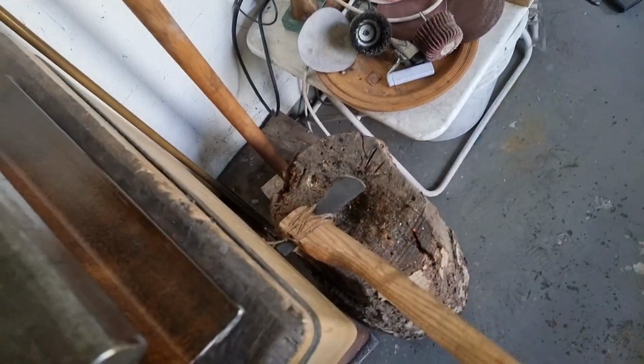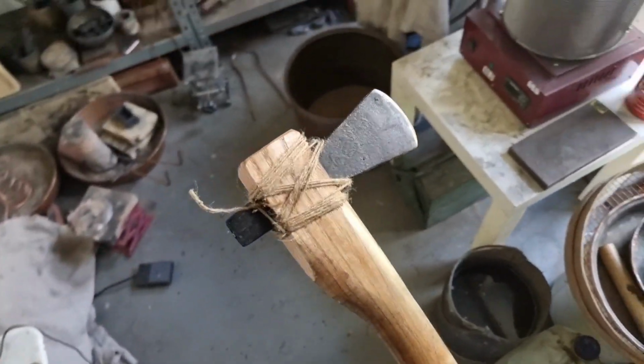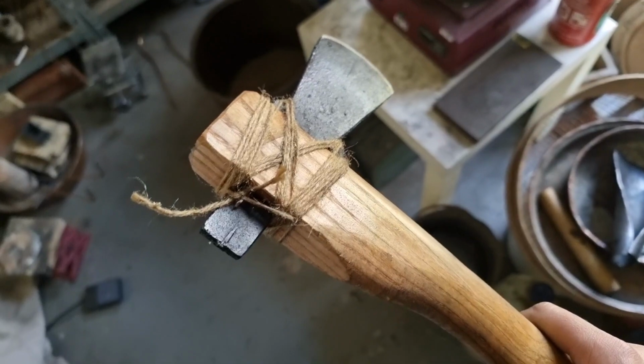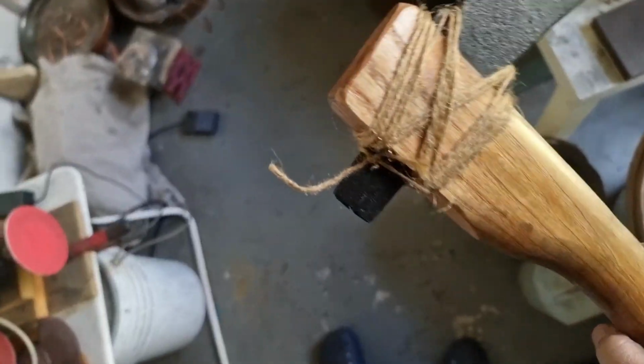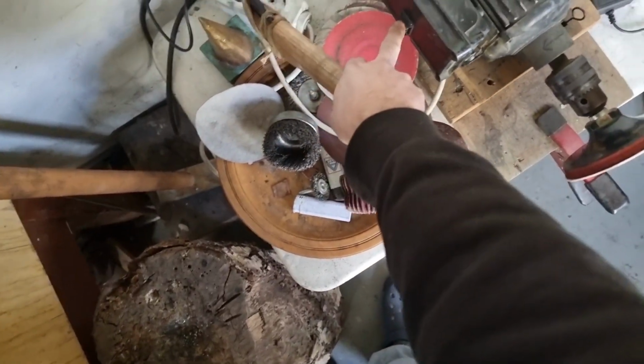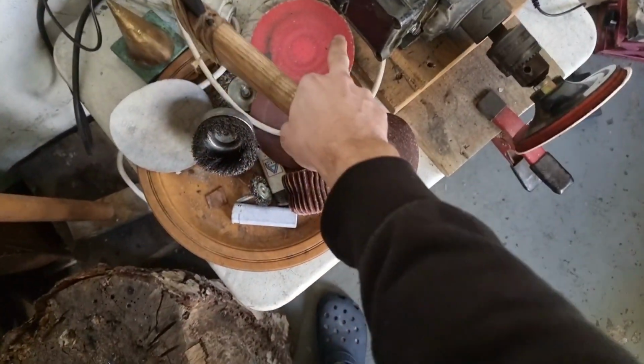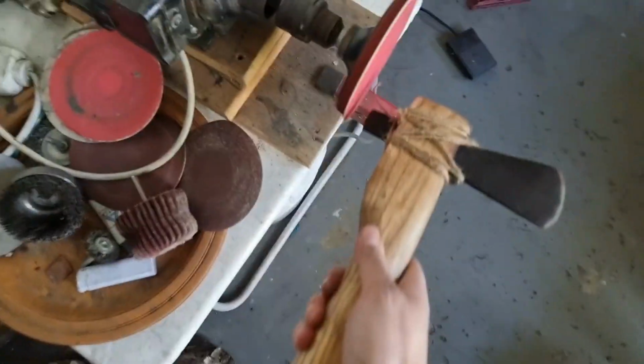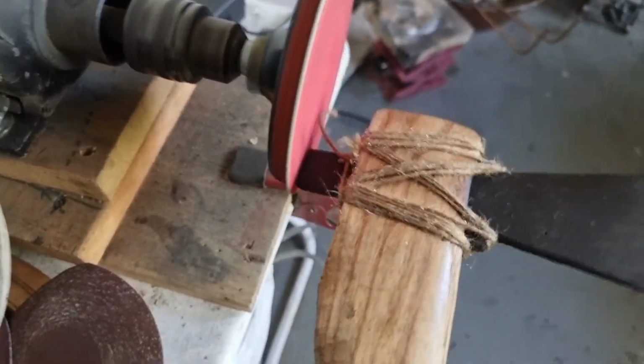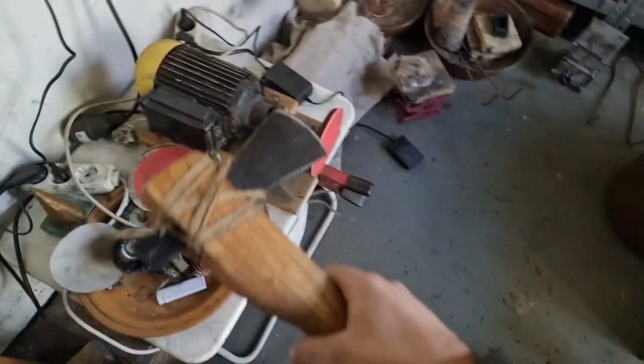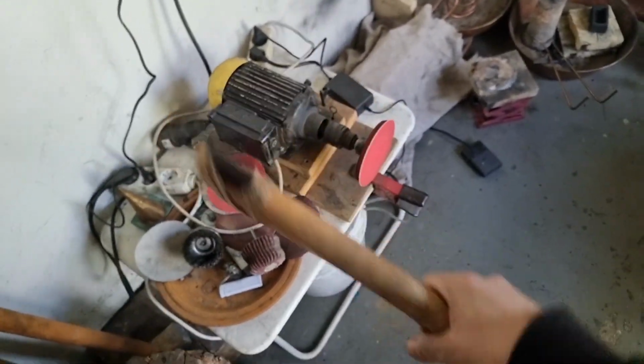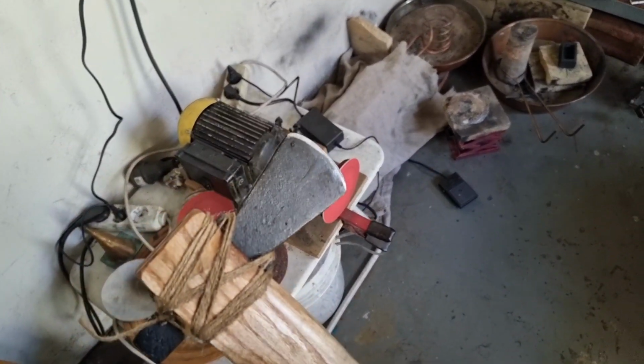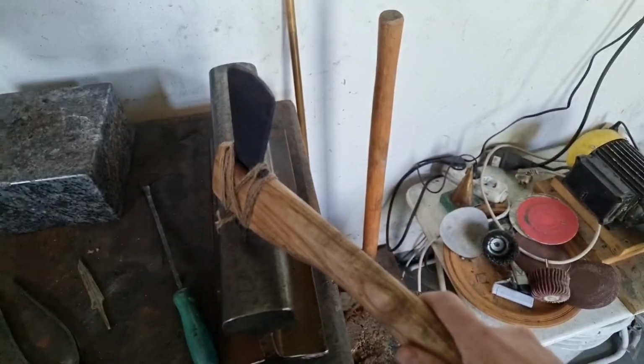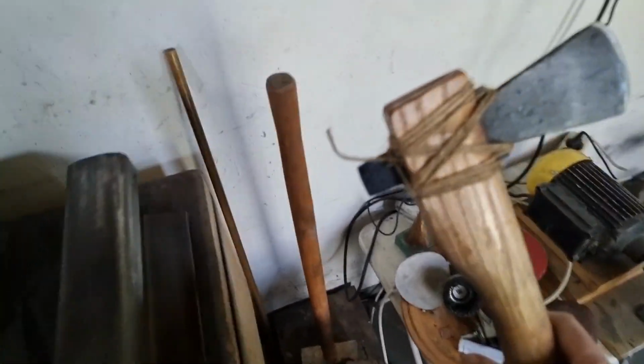Yeah, we also cast the other blade here. Also did the same heat treatment. So this is a cast blade from white cast iron, heat treated for 6 hours or so at 950 centigrade. Yeah. So this also got converted on the surface into steel. So this also makes now quite a robust piece of iron.